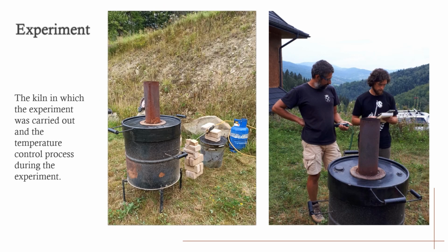For the experiment, a 2-segmented barrel kiln was used, and temperature measurements were continuous thanks to an electronic measuring device with a thermocouple. The weather that day was cloudy and windy with light intermittent rain. Based on the published studies on the experimental fire of wooden buildings, 3 models were defined describing the conditions that could result in secondary burning of ceramics. During the experiments, to recreate subsequent scenarios, 3 pottery fragments were used, while the 4th subsample remained as a reference specimen.